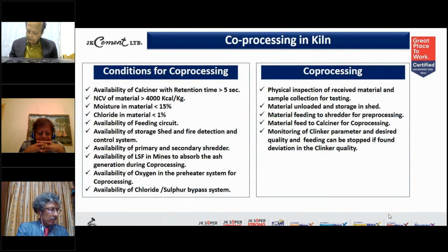When we are talking about co-processing, there are some conditions for it. In the calciner, we have to feed CV of more than 4,000. Moisture should be lower. Chloride content should be lower. The right kind of feeding equipment should be available, and we have to decide about the raw mix and fuel mix. This gives better quality of clinker, and after that better quality of finished cement.